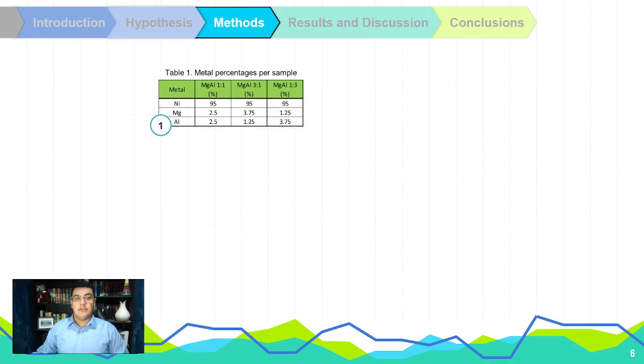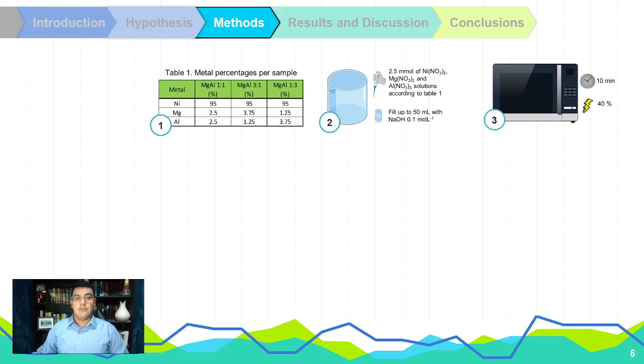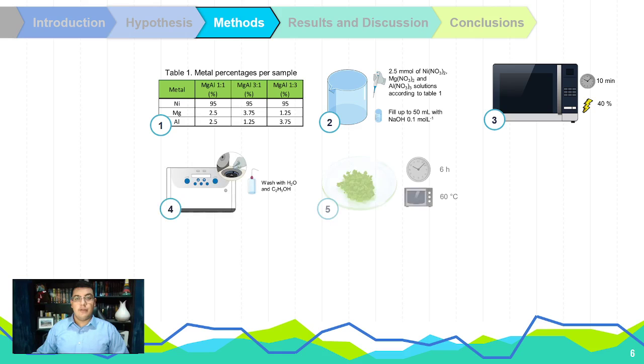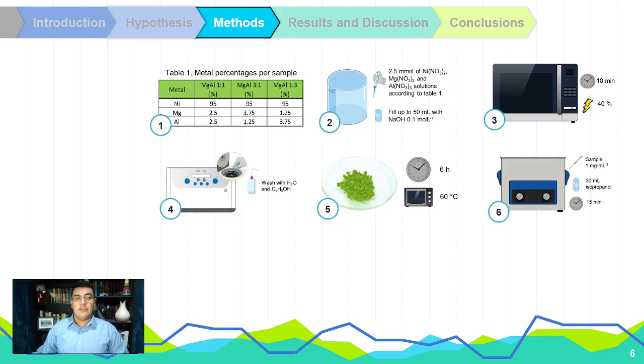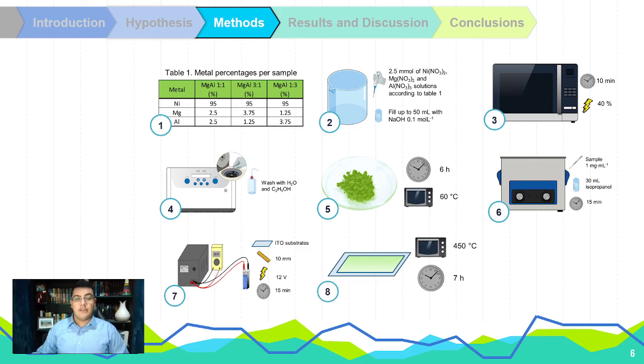Our methodology consisted in selecting the doping proportions to work with. Later, we made different solutions containing the metal ions and adjusted the pH with sodium hydroxide. We took said solutions and subjected them to the radiation of a conventional microwave. We separated and dried our products to disperse them in different solvents and then carry out a series of electrophoretic depositions. At the end, we thermally treated our films and tested their electrochromic properties.